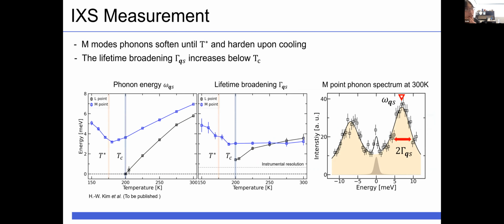Then what could be the origin of chirality? To reveal that, we measured the M phonon temperature dependence. A damped harmonic oscillator model was used for fitting because L and M phonons are heavily damped. Here we plot the fitting parameters.